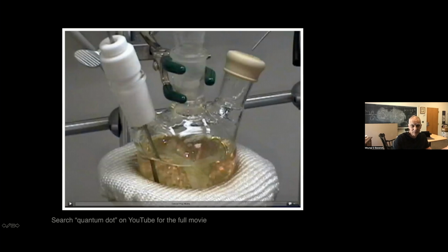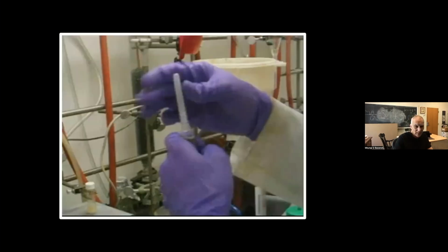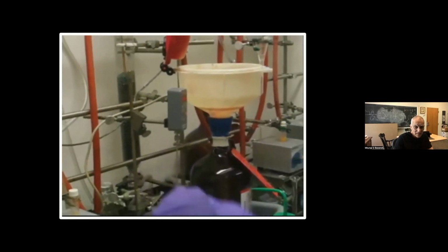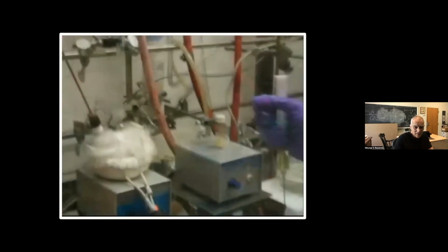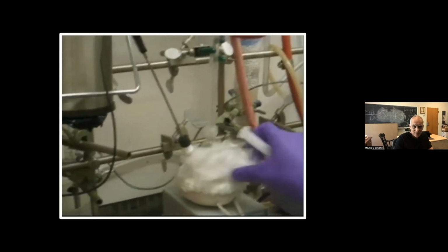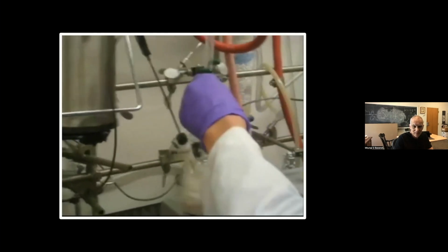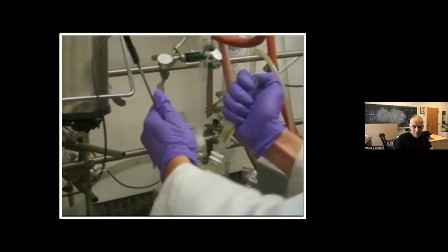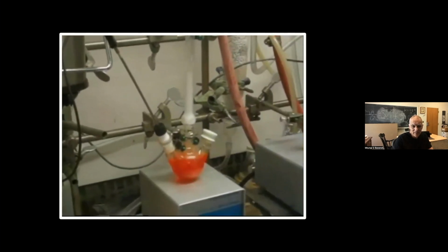So this is a video of this hot injection for making quantum dots. And you'll see then the quantum magic with your own eyes as the color changes, as the particles get bigger. So let's see what happens here. And he's going to do the injection into the hot solvent. Taking the cover off the syringe, and you see this flask that's at 350 degrees Celsius. Quick injection, precursors grow, and you see an immediate color change.